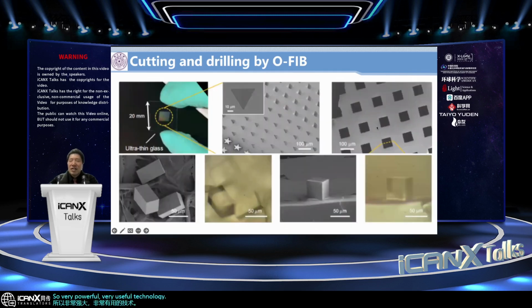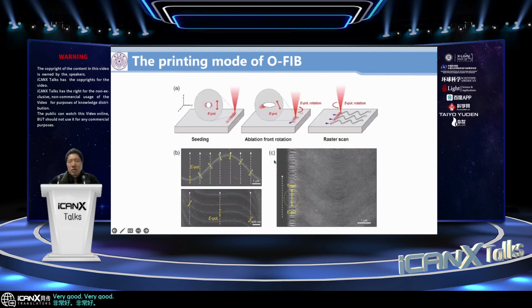And here you can see from a transparent material sheet, we can cut many identical cubes. Certainly, we can cut to form other shapes, small optical components, and the surface quality is very good. The roughness is less than 10 nanometers.